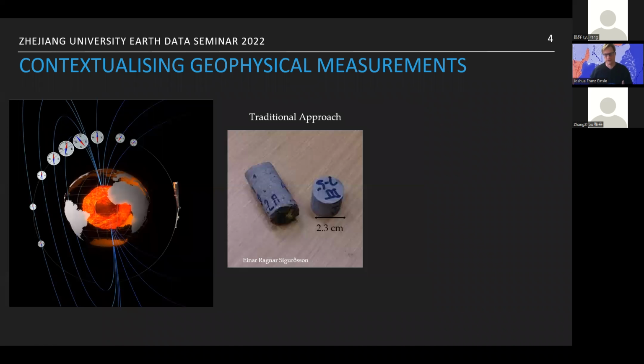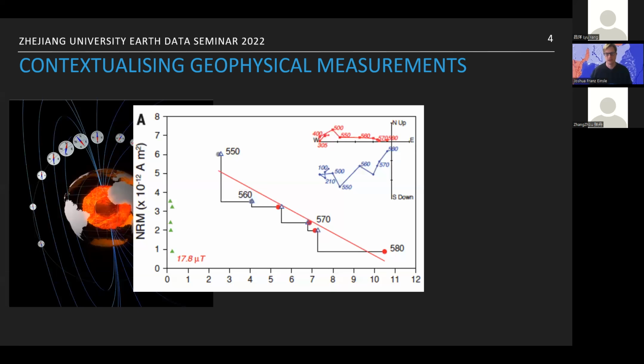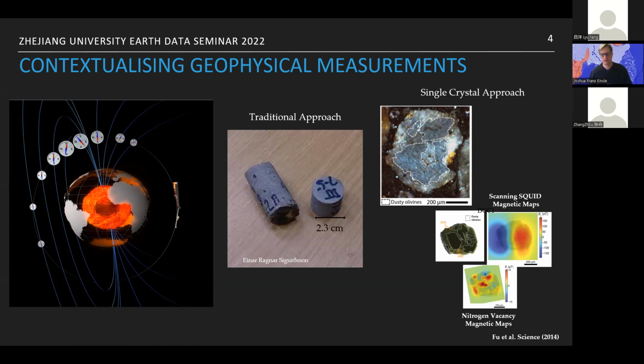However, as I showed here, this is a fairly large macro-scale sample, and this has limits on what we can look at. So in a paleomagnetism sense, there's been a new approach, what's called the single crystal approach, which leverages the fact that we now have very advanced magnetometers that push our spatial resolution, either using nitrogen vacancies in the quantum diamond magnetometer or scanning SQUID magnetometers, down to about the single micron scale. However, even with this advanced single crystal approach to paleomagnetism, we're still averaging over thousands of magnetic signal carriers, because a good paleomagnetic recorder is on the order of 100 to 200 nanometers in scale. So if we want a 200 nanometer recorder, but we only have 3 microns of spatial resolution, like all other geophysical and some geochemical measurements, we're left with the question of what am I actually measuring?